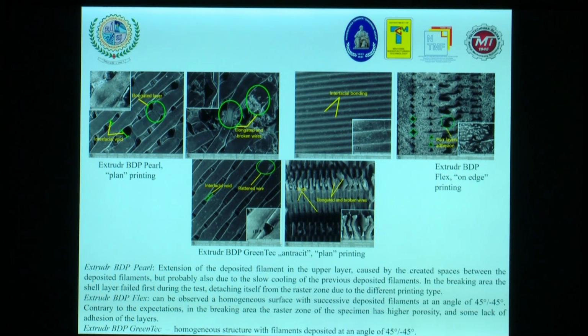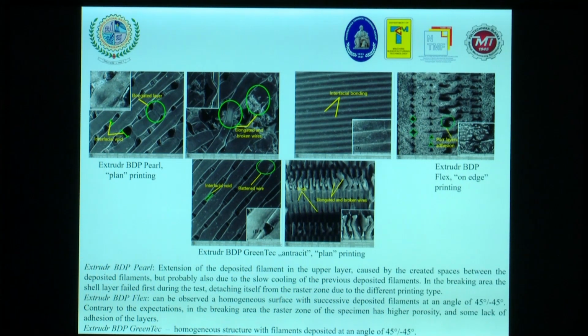Some comments: it's easy to see which is the layer. It's easy to see the extension of the deposited filament in the upper layer caused by the empty space between deposited filaments, but probably also due to the slow cooling of the previous deposited filament. In case of extruded BDP Flex, the second on the right, a homogeneous surface can be observed with the deposited filament at plus minus 45 degrees infill.